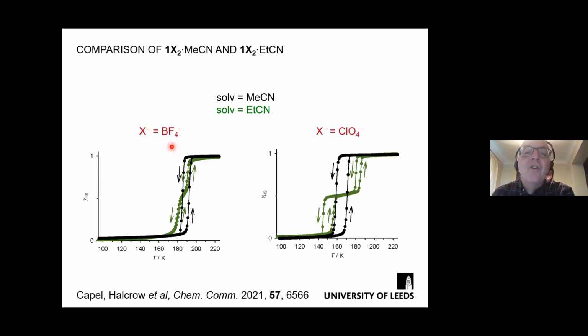The temperature does not change for the 2 solvents. The perchlorate has a little lower temperature than the BF4, and that's a trend you often see when you do these comparisons, because perchlorate is a larger anion, so it favors the larger high spin molecules, lowers T half a little. But when we change from acetonitrile, we have 1 step, to propionitrile, we have 2 steps, but at the same average temperature.